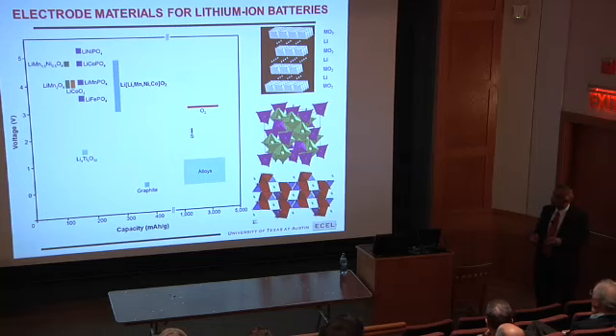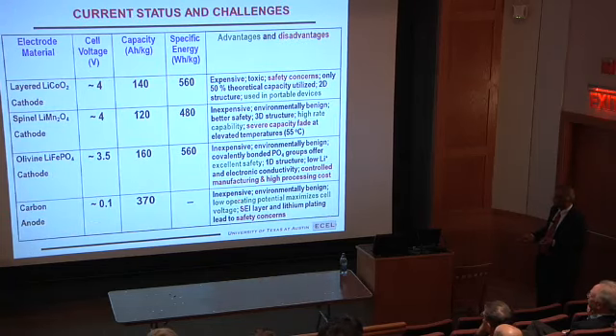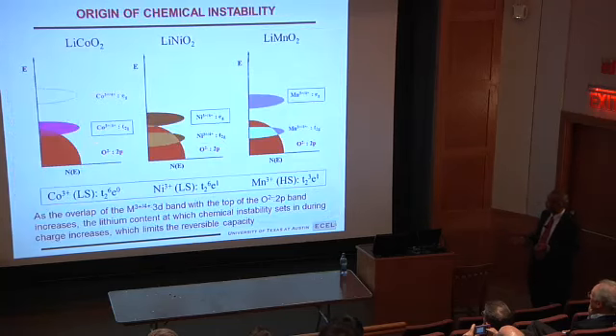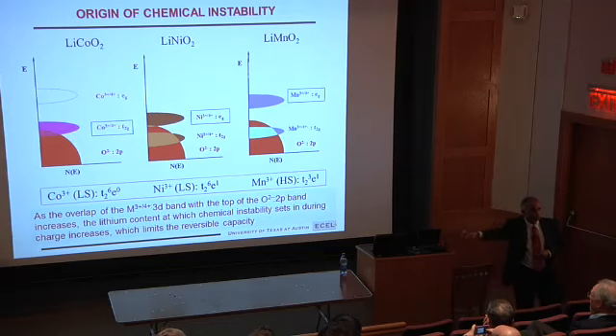Each one of them has advantages and disadvantages. As you see here, graphite has low potential, therefore it can help to maximize the cell voltage. Here, cobalt oxide is good for reversibility, but I can't use more than 50% because, as you see here, this band overlaps with the top of the oxygen 2p. So if you extract charge more than 50%, you not only oxidize or remove electrons from the metal 3d band, you also remove electrons from the oxygen 2p. If you remove too much, then O2- ions can be oxidized to O, and then O2, neutral oxygen, reacting with the electrolyte: explosion, Boeing recall, Dell recall, all those are associated with this.